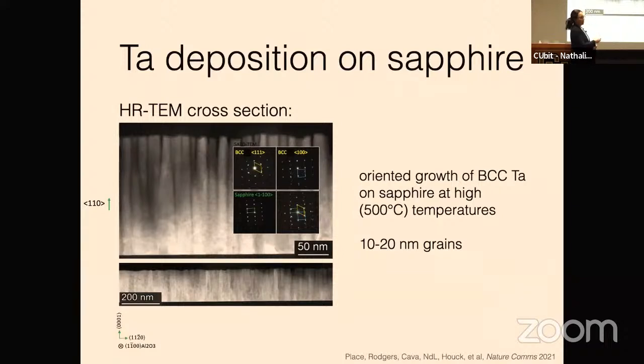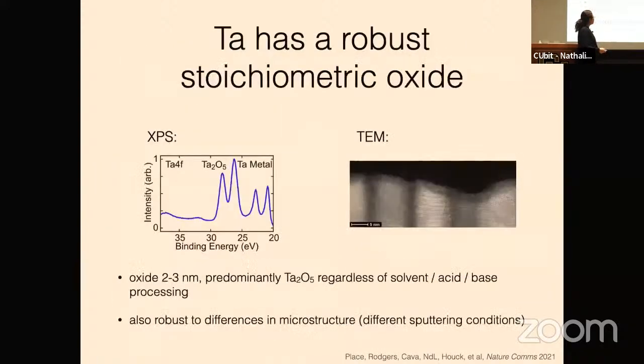And we didn't figure this out. Dan Prober figured this out a long time ago, but it turns out that if you just deposit at a hot temperature and you deposit fast enough, you can promote the alpha phase growth. So we see this nice epitaxial growth, and then as promised, if we zoom in on kind of this amorphous oxide layer, we do get predominantly Ta2O5. It's sort of always 2 to 3 nanometers, almost no matter what you do to it. You just get this kinetically limited stoichiometric oxide.